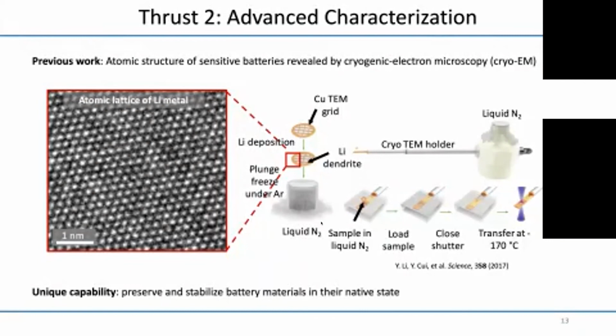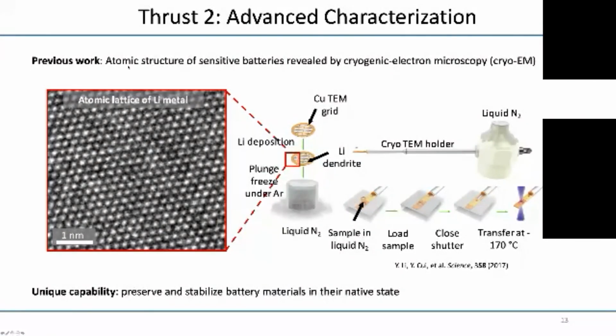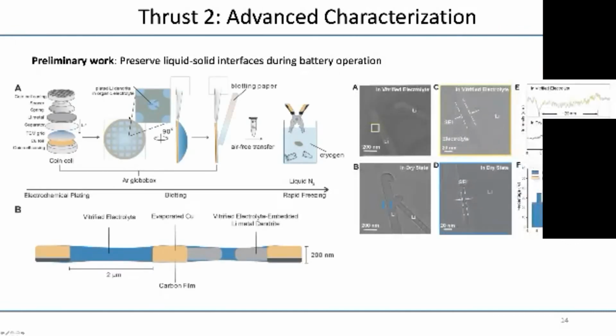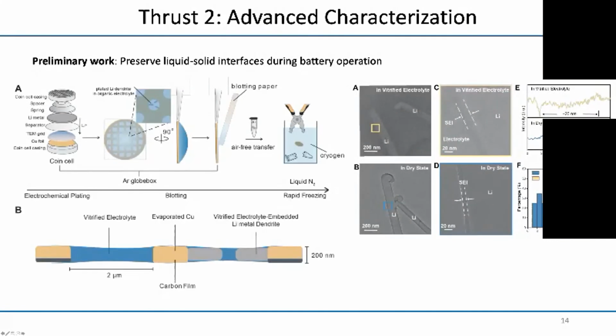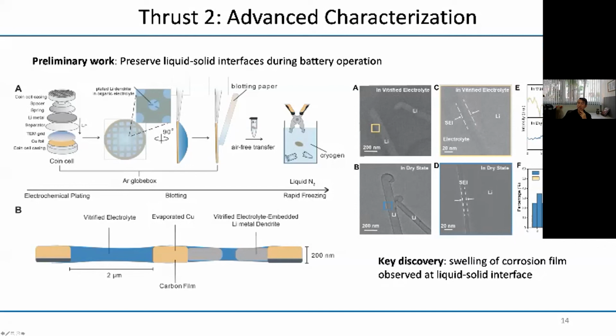And so this technique has this unique capability to preserve and stabilize battery materials in their native state. Some of the follow-up work that came from this initial demonstration is the ability to preserve liquid-solid interfaces during battery operation. For example, when the cathode material is dissolving into the solution, we want to capture that by preserving this liquid-solid interface. I won't go into the details of how we do this, but we essentially take inspiration from structural biology and how they vitrify their samples in making this new discovery of the swelling of a corrosion film that is observed at this liquid-solid interface, again, for the lithium metal anode.